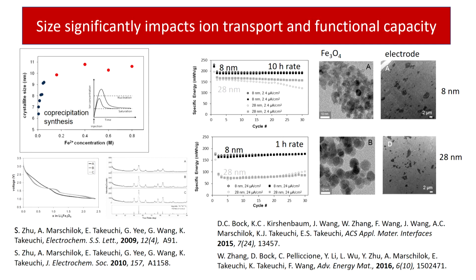Let's move up the length scale a little bit. So magnetite is an inverse spinel, so fairly densely packed structure. By careful synthesis using co-precipitation methods, Ken Takeuchi developed methods where we can prepare these materials without surface treatment or without capping agents. And we find that the electrochemistry is in fact dependent on the crystallite size. And not surprisingly, the higher the rate, a 1 hour rate, we see a bigger difference between the crystallite sizes, albeit both of these crystallites, relatively speaking, are small. You know, we're talking about 8 nanometer, 28 nanometer, but yet we see a difference in the electrochemistry.